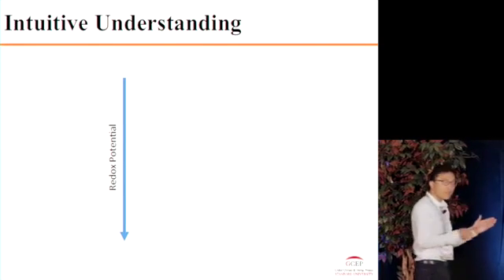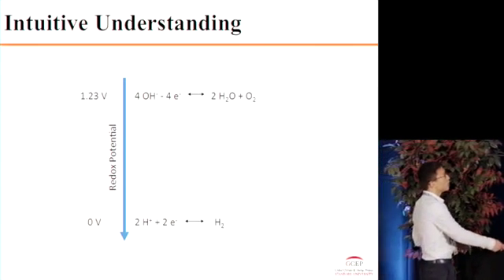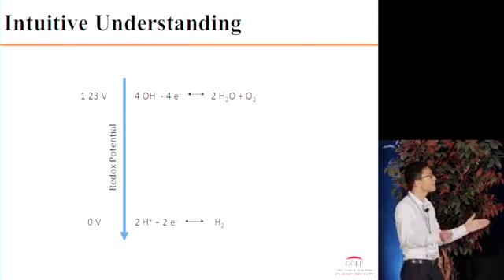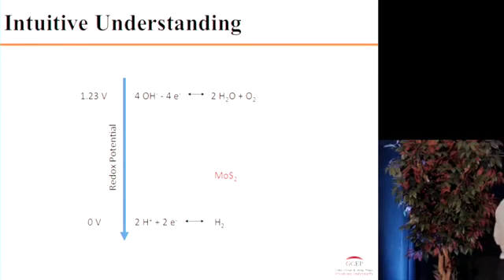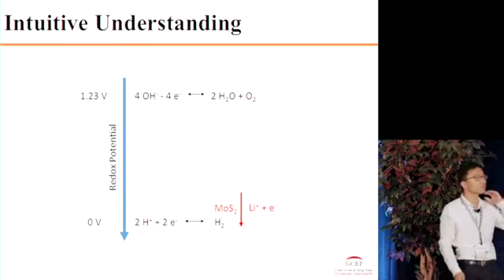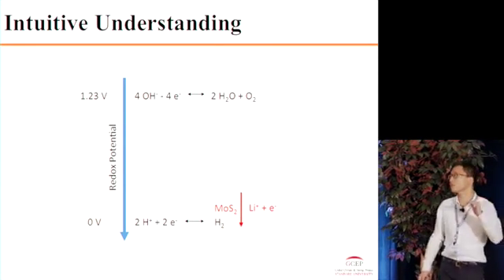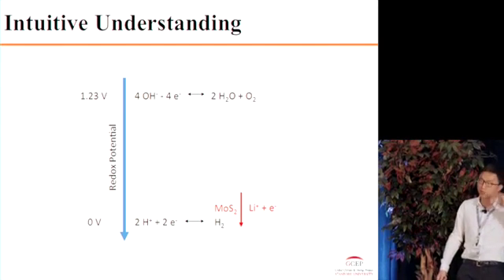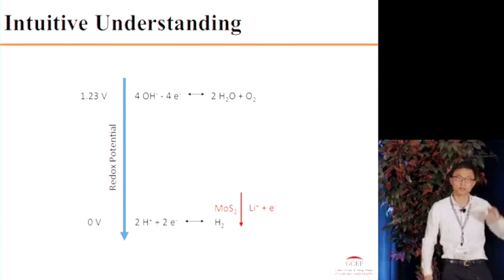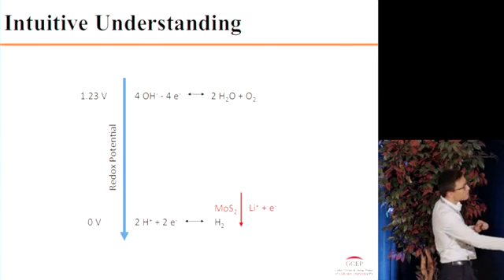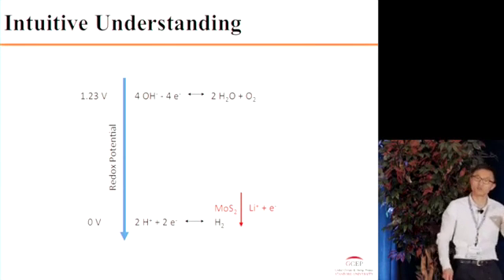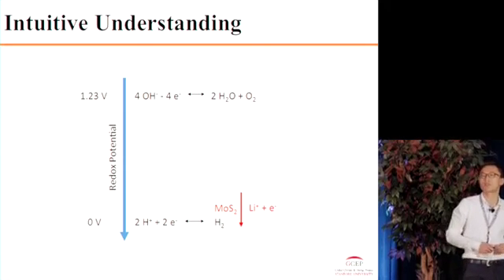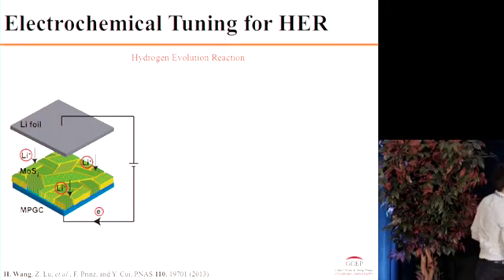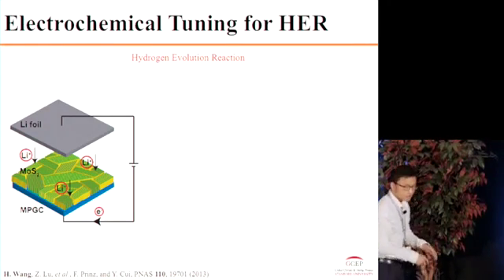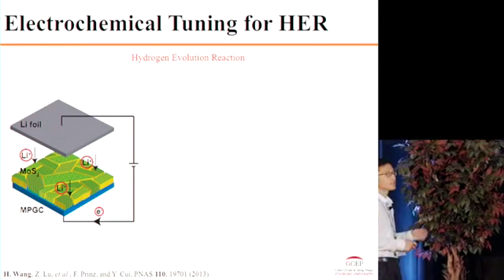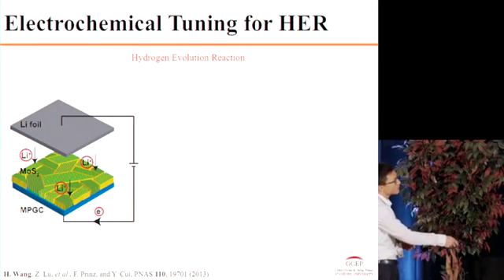So for a very intuitive understanding, for every chemical reaction, we have the chemical potential. And if we intercalate lithium ions into the molybdenum disulfide, we may be able to bring down the chemical potential of the molybdenum disulfide, which may get it closer to the hydrogen evolution reaction and reduce the overpotential by much. So a very easy way for us to do that is to construct a lithium-ion battery and intercalate lithium ions between the van der Waals gaps.